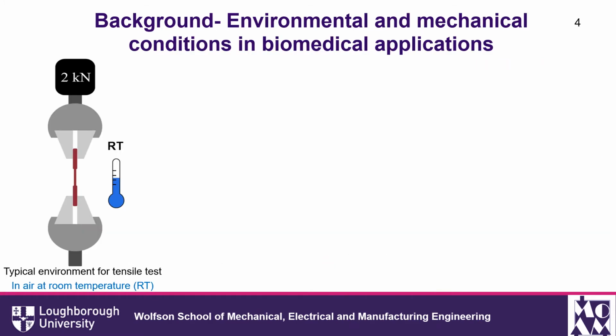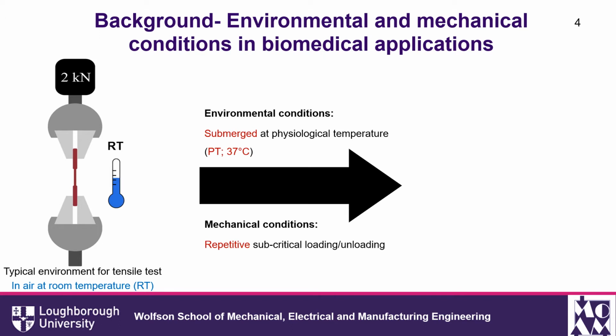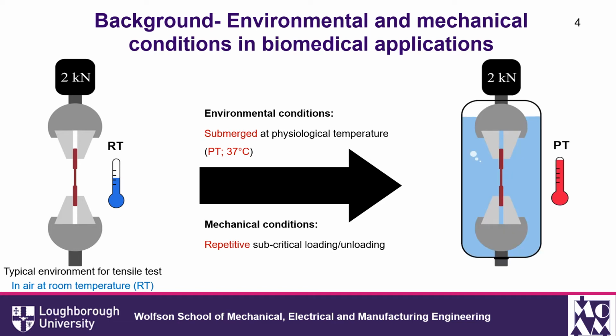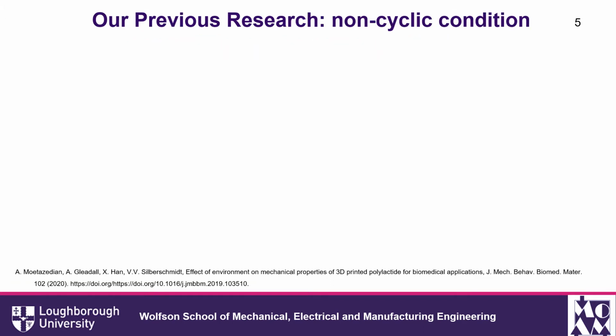presentation. Other than considering the effect of the manufacturing process on properties of biodegradable polymers, it's equally important to understand how the environment changes these properties as well. However, we found that many of the studies in the literature still consider tensile testing in air at room temperature, whereas in vivo, the medical implant is more likely to be subjected to cyclic loading, as well as being submerged at physiological temperature, i.e. 37 degrees. So in this study, we propose a correct assessment of medical devices by performing the tensile testing submerged in water at physiological temperature.